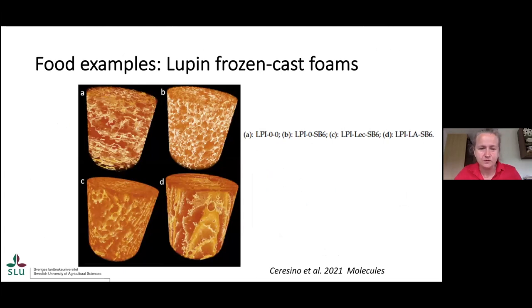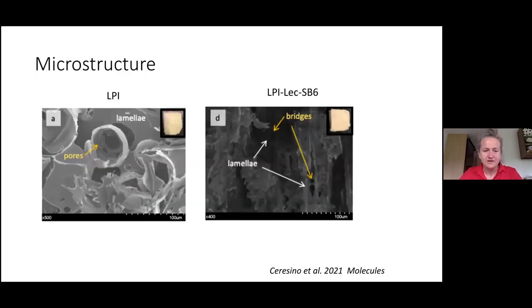Lupin frozen cast foams, we were also intrigued how the structural dynamics is changing by introducing different additives. So if you look at picture A showing no additive, just lupin protein isolate, I should mention that this lupin protein isolate has been produced by dry fractionation, with the idea to make as high as possible a lupin isolate later to be used in different foods. While in image B you see the introduction of transglutaminase, in C you see introduction of transglutaminase and lecithin, and in D you see linoleic acid and enzyme. So there is quite a dynamic change in the morphology of these foams, as well as in the microstructure.